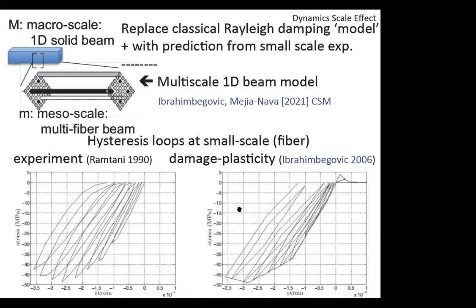And basically the idea is that what we matched is not this beautiful shape of, what do you call it, these eggplant hysteresis loops that are really measured experimentally. We just tried to get the same surface inside each of these hysteresis loops. And this one, which is done linearly, the surface inside is the same. In other words, dissipation in the typical hysteresis loops remains the same. And why is it important that we took linear? Well, because now linear hardening, linear softening doesn't need any iteration. It's one computation, it's done.